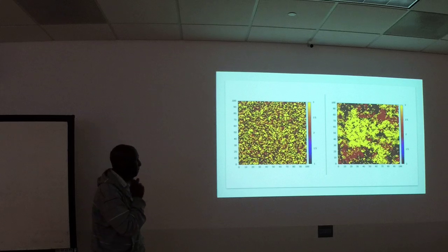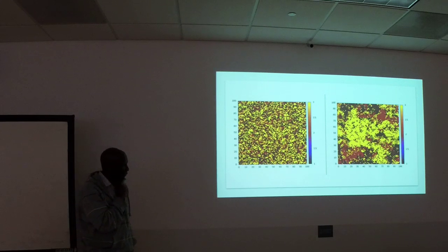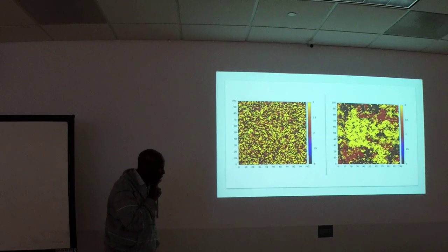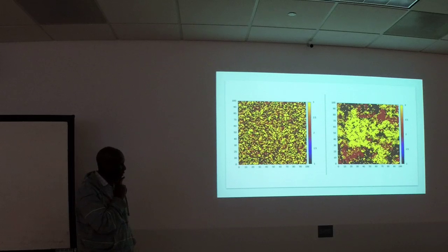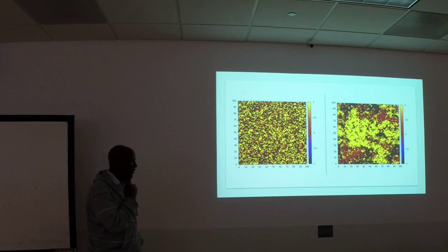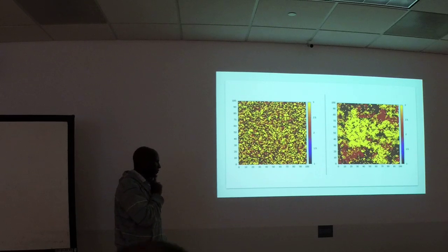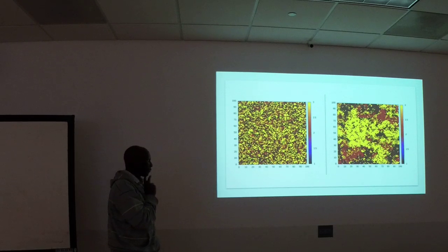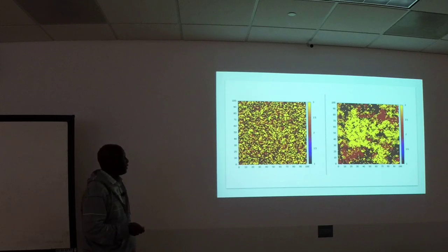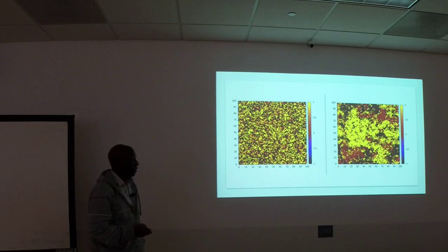It is known, in a variety of fields, both physics, condensed matter, but also what we do with computation, that it is useful to compute things like the size distribution of the domains. As you go through the transition, those domains take on a power law shape. That is, there would be a few big domains and lots of little ones. One way that this research group is used to study the different kinds of transitions, first order, second order, or something else, is to look at the nature of the domain coarse graining through the transition. To collect statistics about the domains is probably hard in three dimensions. I know there are ways to automate it in two dimensions.